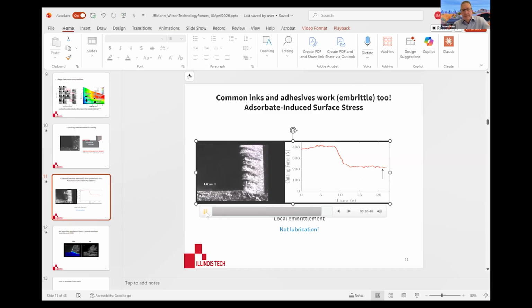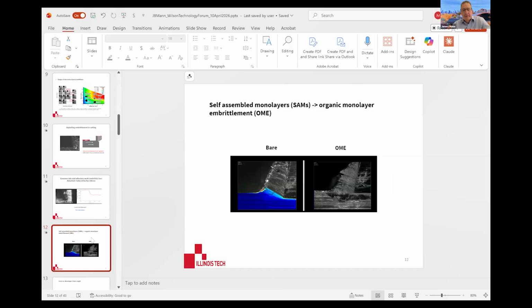And you can see that what happened is not only a completely different type of morphology of the chip, but the actual deformation zone changes, and the force required for the cutting itself drops by nearly half, simply by having a thin layer, in this case, of a benign media on the surface. So this is an interesting phenomenon that we've been exploring and understanding how we could leverage this in this overall approach to materials processing by machining.